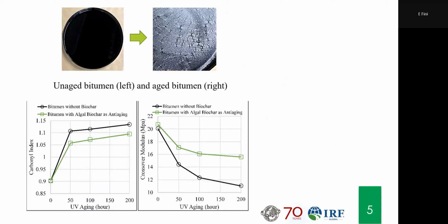One element of aging is actually changes in chemistry. What happens with the progress of time and oxidation? Oxygen is in the air, so it combines with molecules in asphalt, and it forms oxygen-bonding compounds like carbonyl. Here you can see the carbonyl that was measured by Fourier transform infrared spectroscopy, FTIR, that most of you are familiar with. And we calculated the increase of carbonyl over the aging time. If the material did not age at all, the carbonyl index would not go up because there is no more oxygenated compound. This carbonyl is basically a C=O compound, the combination of oxygen that is now bonded with carbon. So these carbonyl groups go up as the aging progresses.